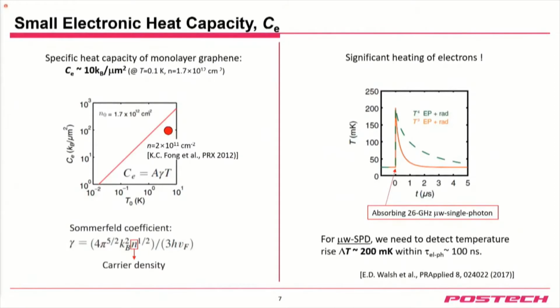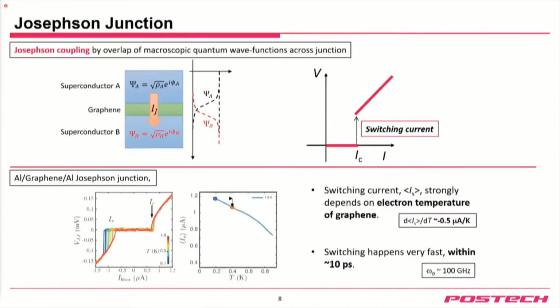So the question is, how can we measure a change in electron temperature of 200 millikelvin within a thermal time constant of about 100 nanoseconds? That's why we incorporate the Josephson junction concept. Basically, a Josephson junction is two superconductors coupled through a non-superconducting material, which in this case is graphene. When the superconductors are close enough and the graphene is conducting enough, then a supercurrent can flow by overlapping these superconducting macroscopic quantum phases.